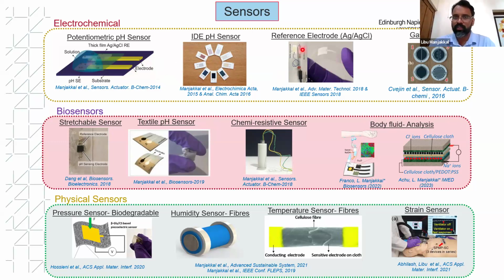This is one of the reference electrodes. You can see from here that this is a commercial reference electrode and this is a thick film reference electrode, and later I modified this into a flexible reference electrode. Here you can see the silver chloride. In brown color you can see a silver layer, and on top of that is the KCl paste I prepared, which I printed using a screen printing method.